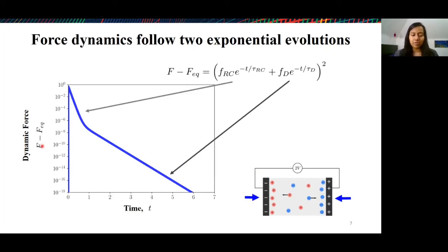Here, the dynamic force is the transient force subtracted by the equilibrium value. So I've removed the equilibrium contribution to the force, and this is just the transients. This is a log linear plot, and you can see that the dynamic force seems to have two sort of straight line evolutions. A straight line in a log linear plot indicates an exponential decay. So this basically means that the dynamic force is composed of two exponential decays.